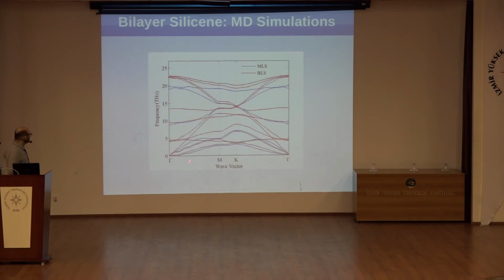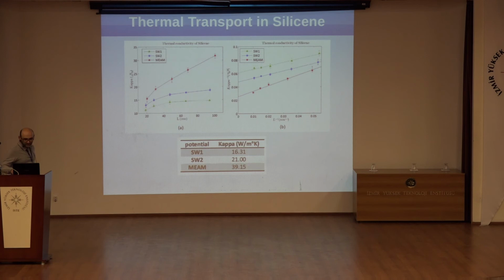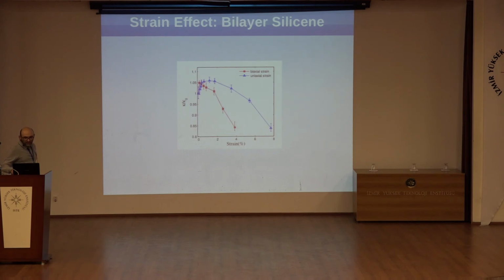It is possible to see the reason. As you see, for the case of bilayer silicene, the acoustic modes have a higher group velocity, and it led to higher thermal conductivity. Finally, I will briefly discuss the effect of strain, as discussed in the previous talk as well. It is possible to change this by imposing a strain. It is possible to get different thermal conductivity in bilayer silicene.